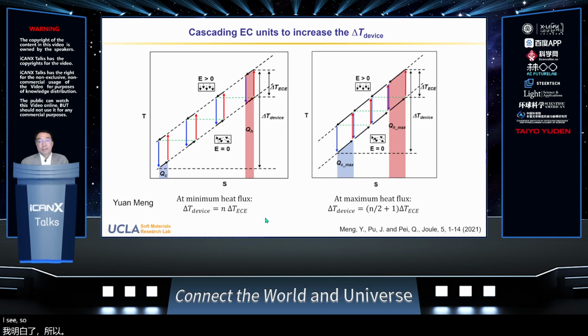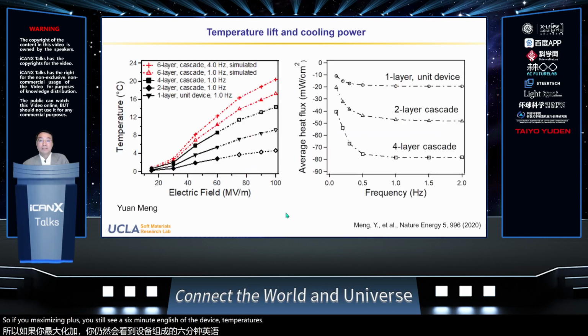So if your delta T ECE, the property of the material, is 3 Kelvin, and you have 4 layers stacked, ideally you would have 12 K temperature lift from the device. So if you maximize the heat flux, you still see a significant increase of the device temperature span. So this is what we got.